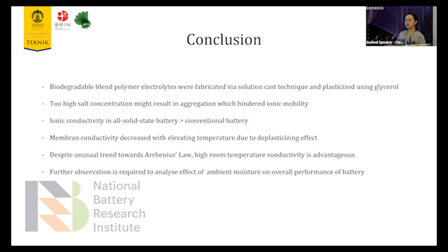So in conclusion, we have fabricated a solid polymer electrolyte using biodegradable materials via the solution cast technique. The first finding is that high salt concentration might result in aggregation, which hindered ionic mobility. We also found that we can actually make a solid polymer electrolyte in an all solid state battery that is better than a commercial battery with liquid electrolyte. And the third finding is that the membrane conductivity decreased with elevating temperature due to the plasticizing effect.